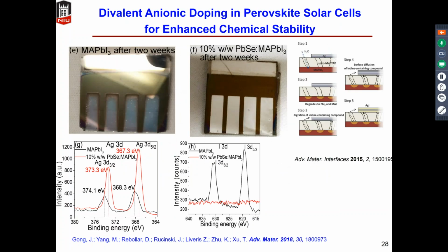Another bonus that we got by doping this divalent ion, such as selenide, is this. It is known that the iodine in the perovskite layer can actually migrate, especially when silver is used as the counter electrode, because considering the high cost of gold, many groups now start to use silver as a counter electrode. But the migration of iodide through the hole transport layer will cause the reaction between iodine and the silver and form silver iodide. As you can see, this silver electrode-based perovskite always suffers from the formation of silver iodide